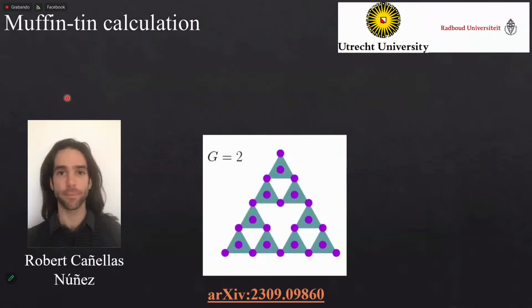So to understand this, I will now describe the theoretical part of the work. We have this material that is flakes of bismuth. And as I mentioned to you, bismuth is a material with a very high spin-orbit coupling. So to describe the theory of the system, we're going to use two approaches. One of them is a muffin tin method, where we start with free electrons, then add potentials that confine the electrons to some region, and then introduce the spin-orbit coupling. The other way is the tight binding method. So now we're going to start with the muffin tin, and then go to the tight binding.